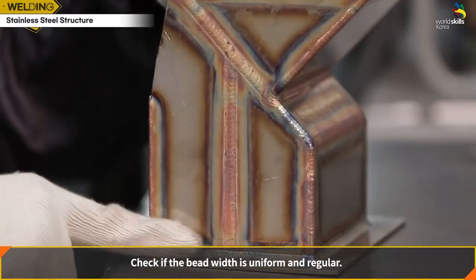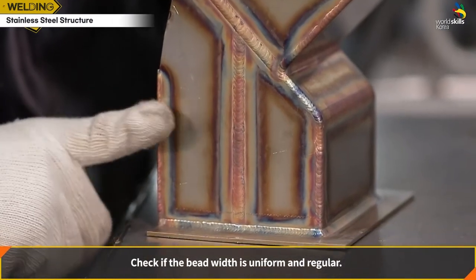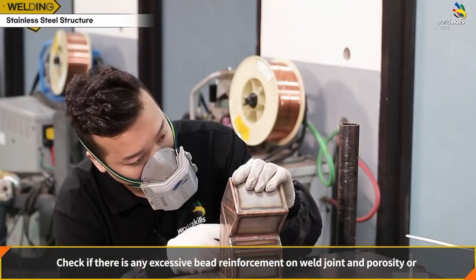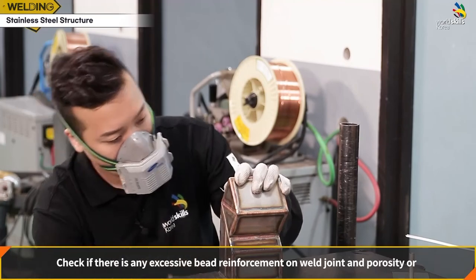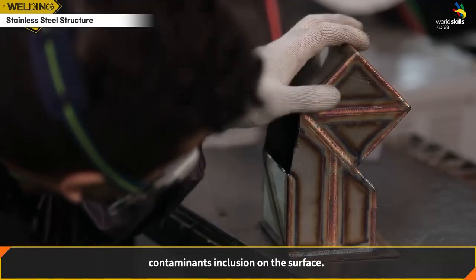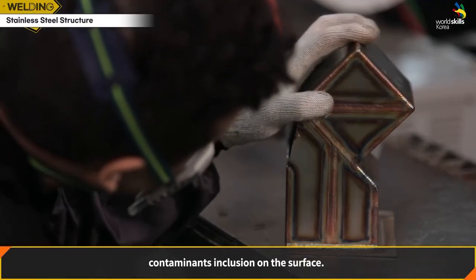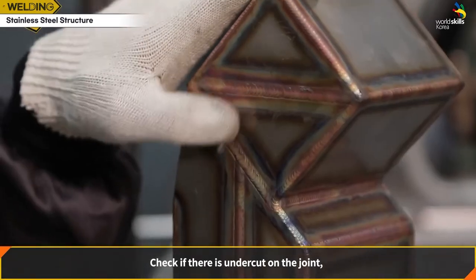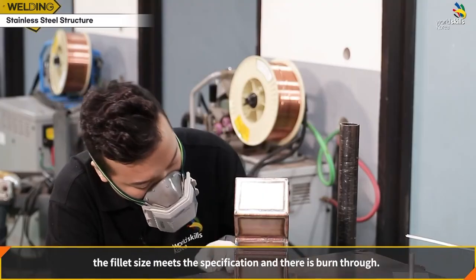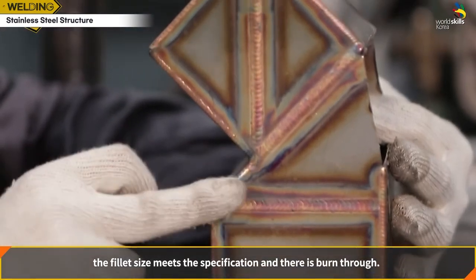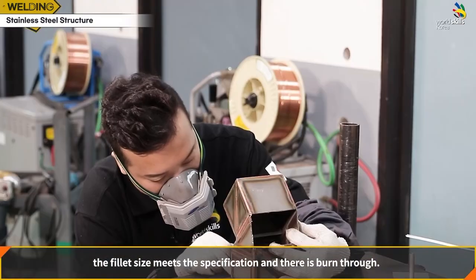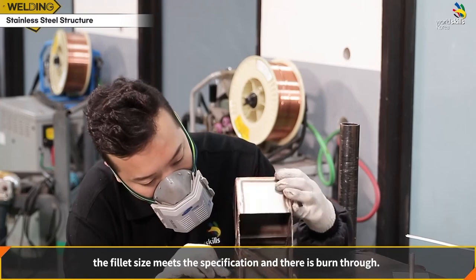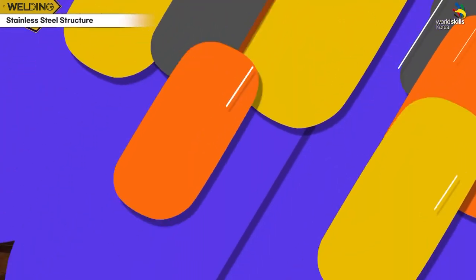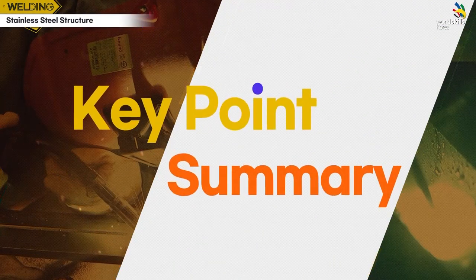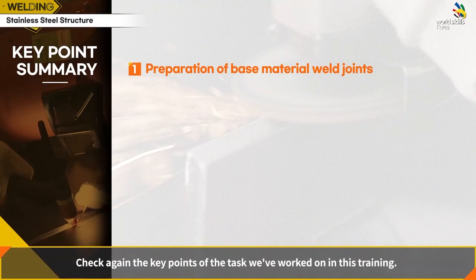Check if the bead width is uniform and regular. Check if there is any excessive bead reinforcement on the weld joint, and porosity or contaminant inclusion on the surface. Check if there is undercut on the joint, if the fillet size meets the specification, and if there is burn through. Please check the key points of the task you have done this time.